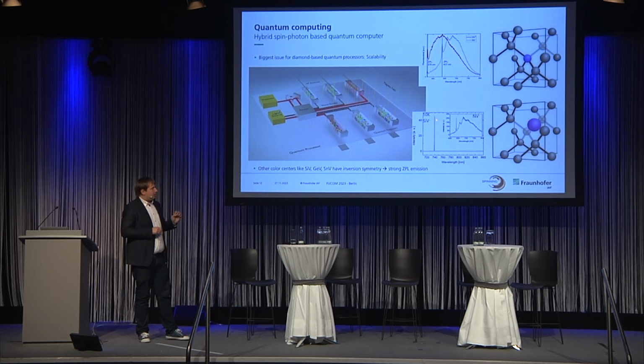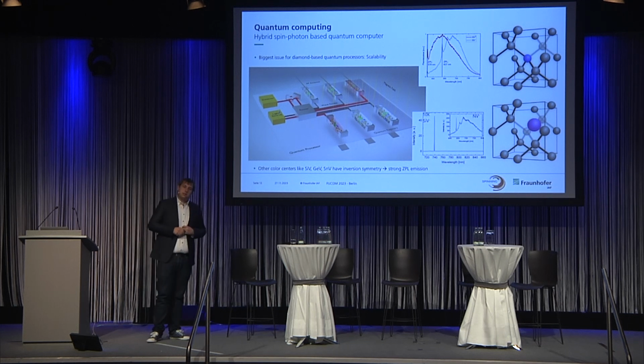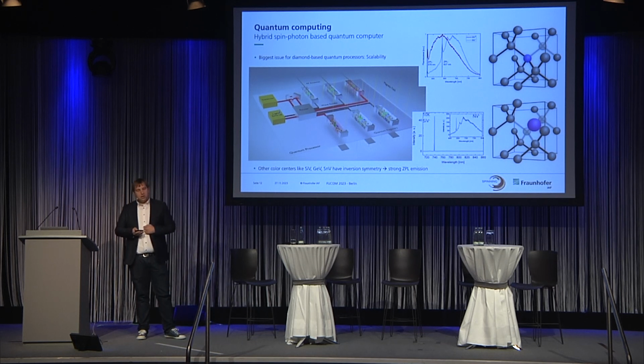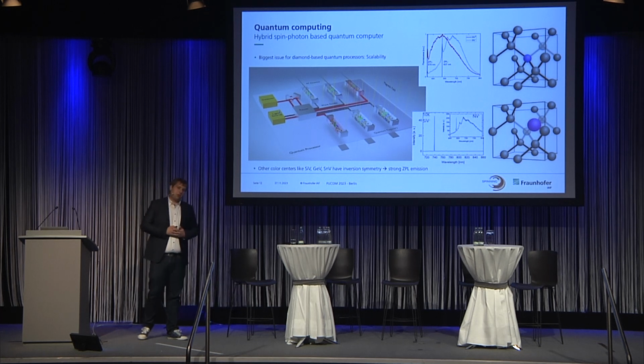Problem with SiVs is, you see here, this is 10 Kelvin. You cannot use them anymore at room temperature. So this is another approach that we're working on that may actually lead to larger systems, apart from the dipolar coupling that still has challenges in positioning accuracy.